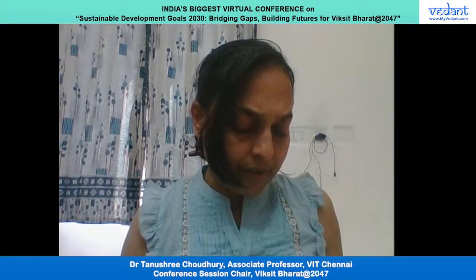And in the last, that is the carbon footprint reduction potential, which the authors gave through a bar chart, it showed that there was a 50% reduction in the carbon dioxide footprint based on the various grades of clinker that they have used. Since they have shown a 50% reduction in the carbon dioxide footprint, this is a very good initiative taken towards the minimization of the carbon footprint.